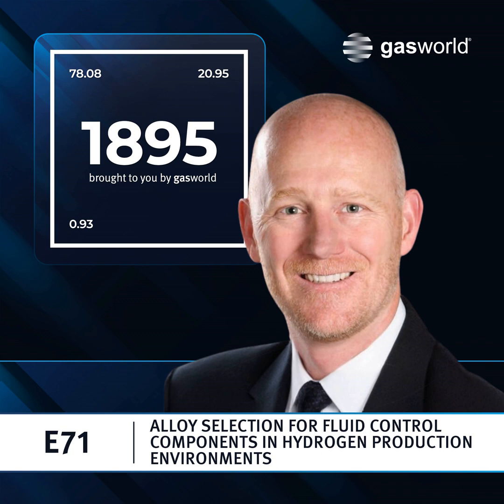So the temperatures are modest, on the order of 50 to 90 C, and the pressures are also modest, on the order of 35 bar, 500 psi. But the solution is anywhere from 20 to 40 weight% potassium hydroxide or sodium hydroxide, and that solution is of that composition to improve the electrical conductivity of the solution. But it also generates caustic corrosion concerns for some of the components, particularly the low alloy steel components in the stack.